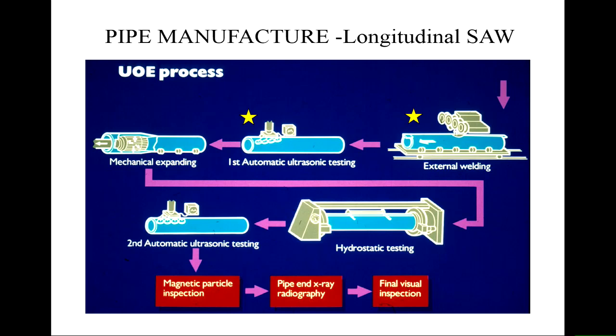After you do that, you do another automatic ultrasonic test just to make sure you haven't produced any defects during hydro testing. So by the time that comes out, and you might do magnetic particle inspection, pipe end X-ray and radiography, or even final visual inspections, you should be able to guarantee as a steel supplier that each pipe segment that you deliver is fit for purpose.